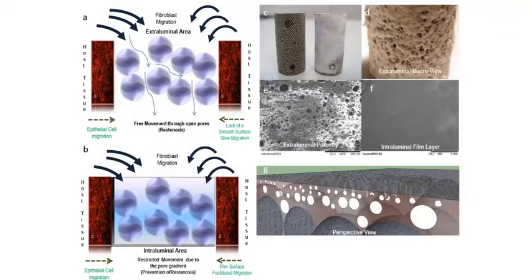In this current case, in our previous studies with porous titanium implants, one thing we noticed is that our control over cell movement in vivo was not high, and this study was aimed to improve that control. First, by adding a microporous PLLA body between the open pore structures within the titanium. And secondly, by having a film layer — a basement membrane-mimicking film layer based on collagen and alginate — to improve the movement of epithelial cells in vivo.